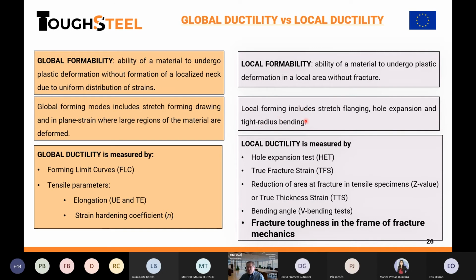This local forming includes stretch flanging, hole expansion, tight radius bending, and so on. And the way we can measure it, well, there are some quite experimental tests based on strain and fracture observations, like the hole expansion test, the true fracture strain, reduction of area at fracture in tensile specimens, also the bending angle. These parameters are quite easy to get, but they are not really mechanical properties of the material. So as material scientists, we would like to know which material property we can use to understand cracking. The answer to that is the fracture toughness.